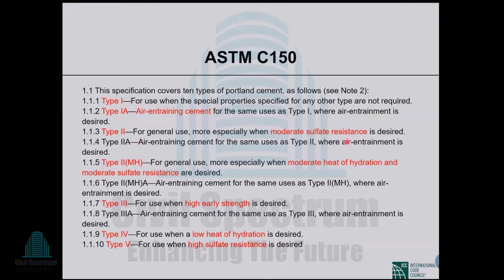Type 2 is moderate sulfate resistant cement. In BDS EN also, for sulfate resistant cement, there are different classes like CEM1 SR, sulfate resistant CEM1, CEM2 SR. But in our market, those types are not available. But the standard has specifications for those types of cement. So in ASTM, the moderate sulfate resistant cement, moderate heat of hydration, this is very important. We often feel that for mass concreting, if the heat of hydration could be reduced, that would be better. If these types of cement are available, then we could use them in those cases, like type 2 MH, moderate heat of hydration. Heat of hydration is less than the ordinary Portland cement, and moderate sulfate resistance.